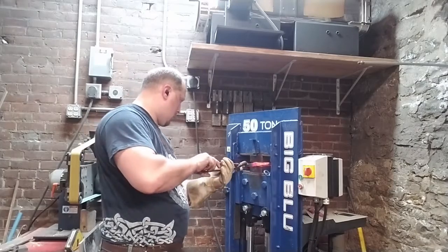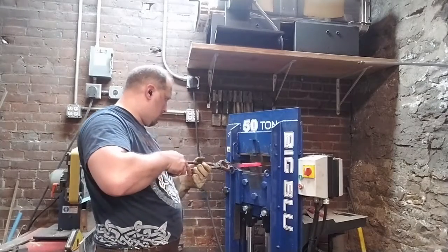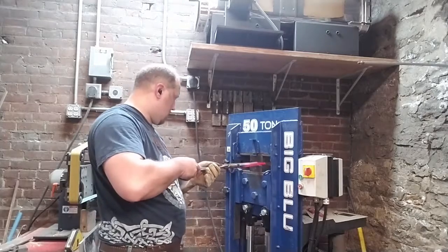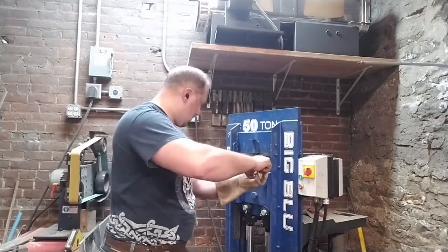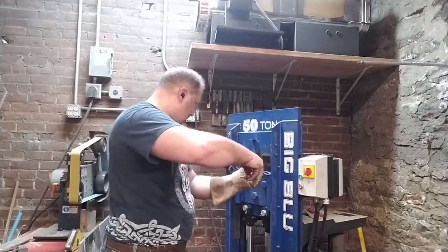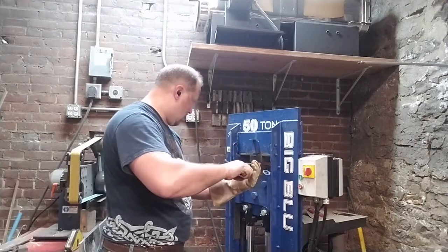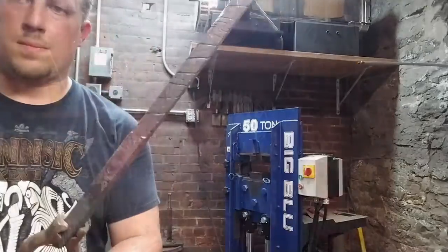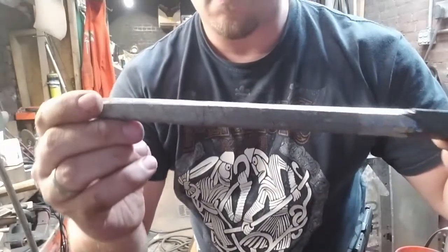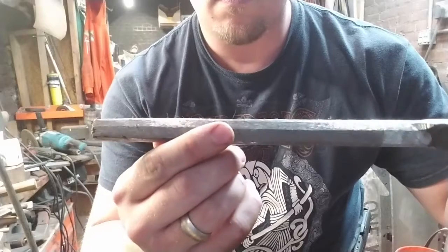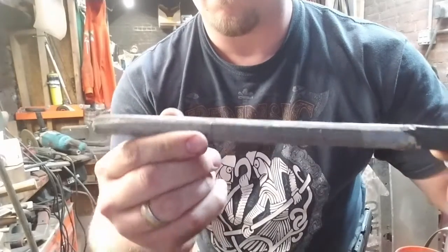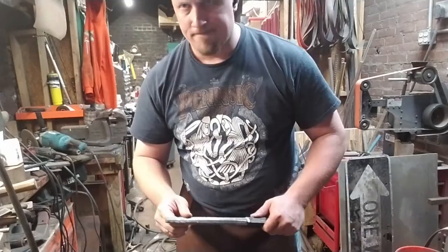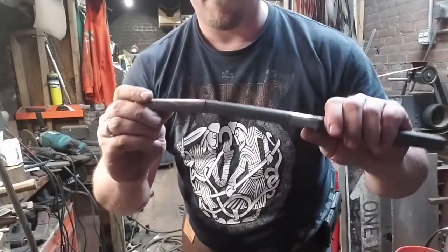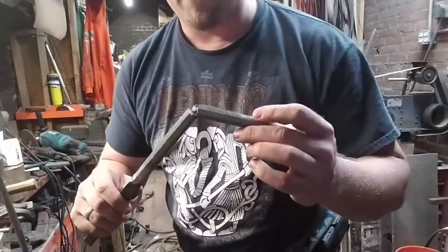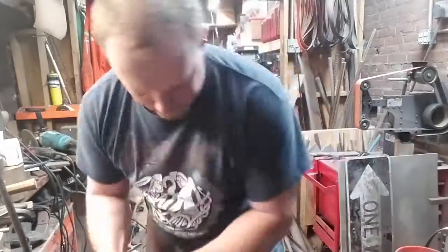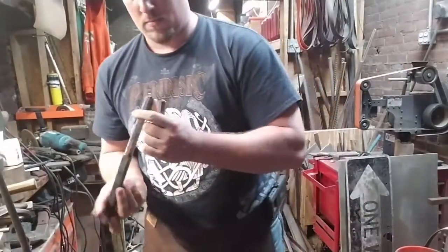As soon as you begin a twisting process, there will be points on your twist that will go faster and some will go slower. And if you want a nice even twist, it's very difficult to work out artfully. So if something starts to over twist, the best thing that you can do is stop. But I didn't stop fast enough, and I'm pointing out that even though we forged that out, there's still a crack there. I'm just going to go ahead and break that off, and we'll grind it down and work with what we have left.